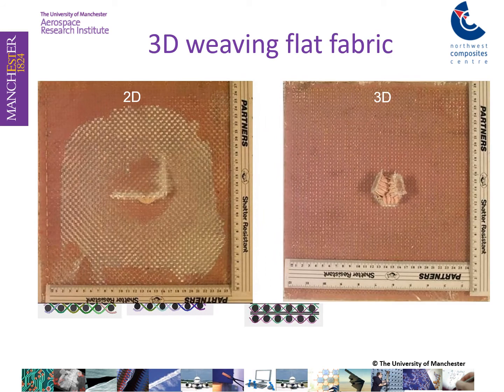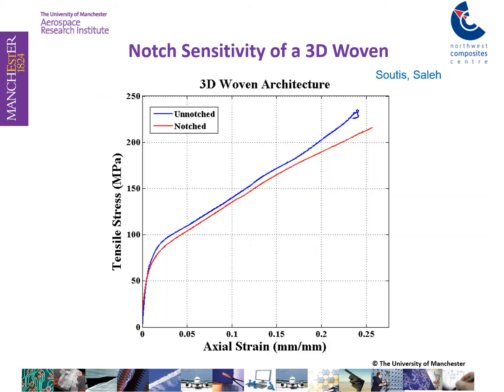This is a comparison between the two-dimensional fabric and the three-dimensional construction, where we can see on the left-hand side extensive delamination is taking place, but on the right-hand side, the 3D fabric, you have no delamination. You do get fiber breaks in both of them, but no delamination. And then the challenge is when you have these broken fibers, you have this open hole. Can your laminate accommodate the hole without actually suffering in terms of losing strength and stiffness?